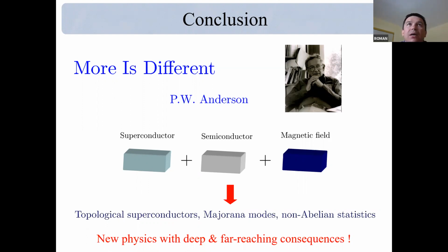And parameters, that's a good point. We ask our experimental colleagues to do specific experiments to determine these parameters. For example, the value of the band offset was studied using ARPES. There are also experiments running STM to understand what happens at the interface. For the value of spin-orbit coupling, we use weak antilocalization measurements to extract this parameter. So there are dedicated experiments that we use to extract parameters.